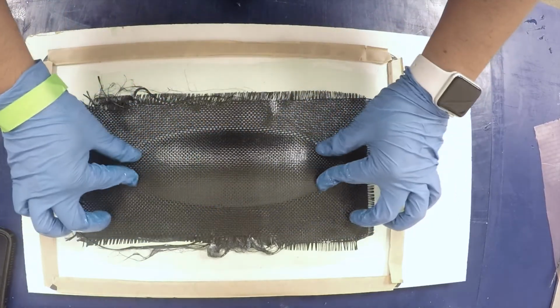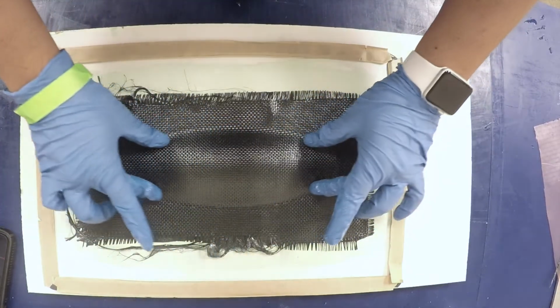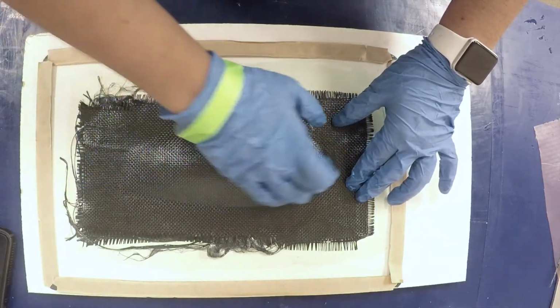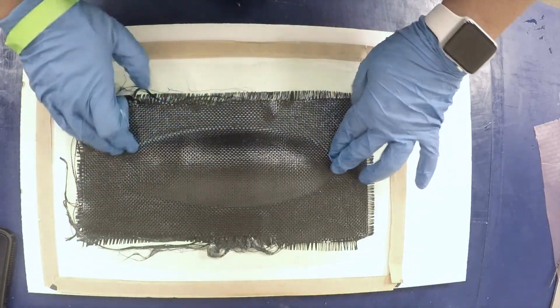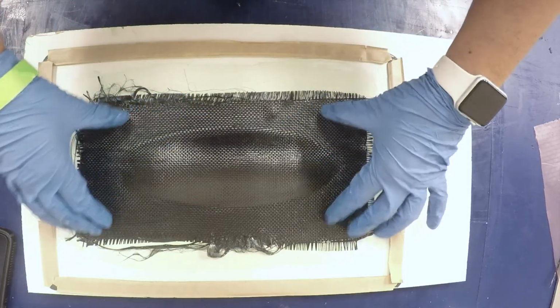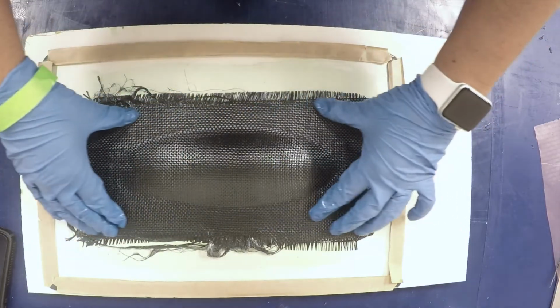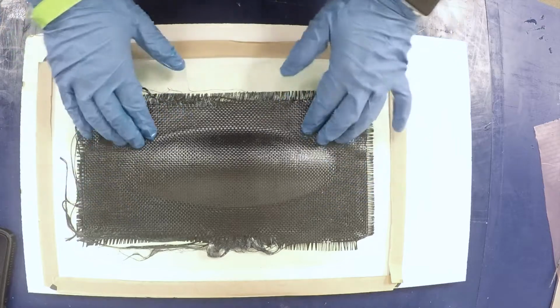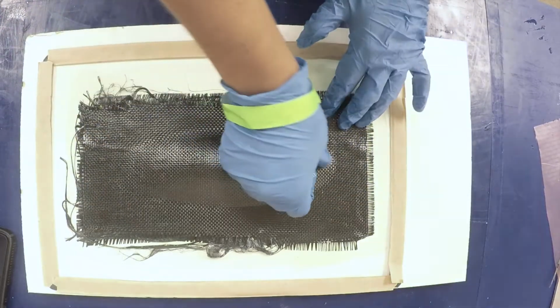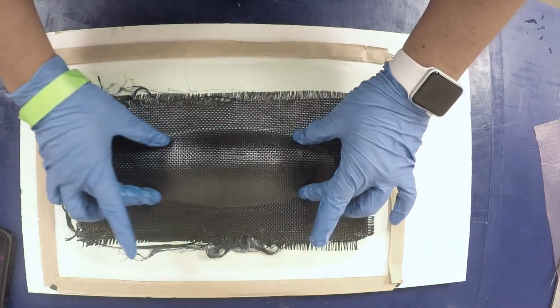Once you have placed down all of your layers, feel around your mold to see if you can notice any bridging or gaps or folds inside of the laminate that you may not be able to see. All of these will negatively affect the final part of your surface. A tight fit around the mold will produce a geometrically accurate and smooth final product.